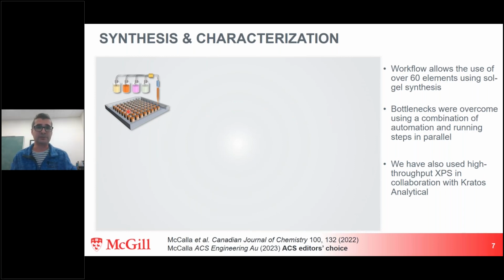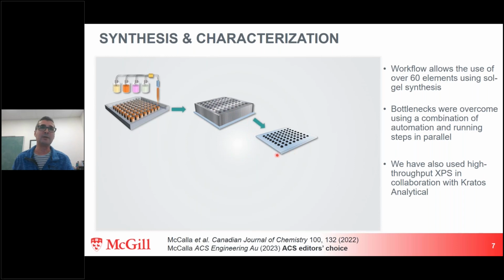So we basically use a chelating agent like citric acid, and then dry the samples into gels that are well mixed, and then heat them to higher temperature. So we use this, I call it a smokestack. It's a piece of aluminum with some holes in it, and it just prevents all these little samples from mixing. And then after heating to really high temperature, for sodium-ion batteries it tends to be 850 degrees Celsius, we end up with small cathodes, essentially. So these are about 5 milligrams in scale, to give you an idea. These cups are half a milliliter, so they're about this big.